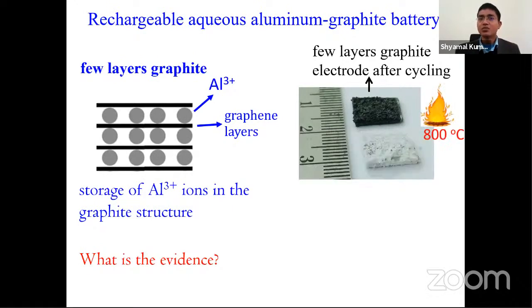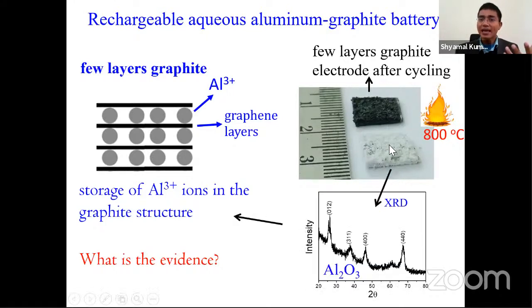And when we did it, you see that this black product turns into a white product. When we performed X-ray diffraction of this white product, we found that it is basically aluminum oxide. So this black product turned into aluminum oxide. That means the aluminum ions are there in this graphite, and when you burn it, the aluminum turns into aluminum oxide and the carbon just goes away. So this is how we prove that the aluminum ions are really inside this structure.